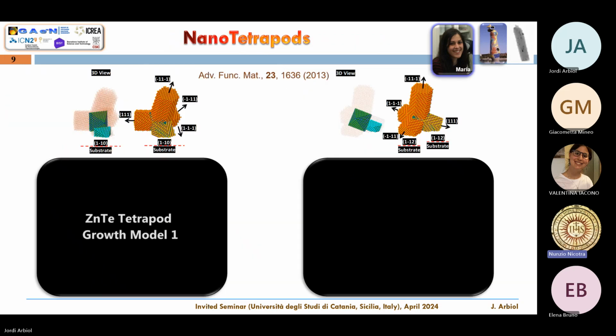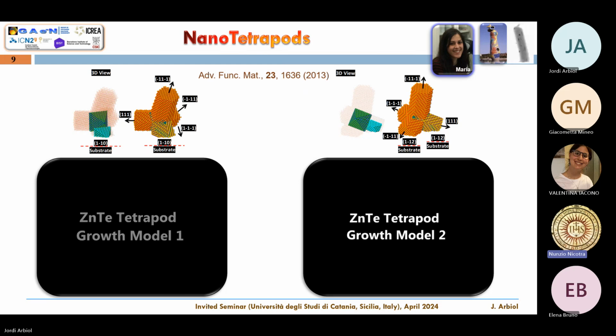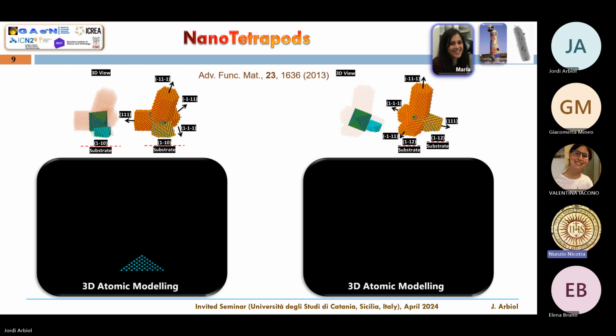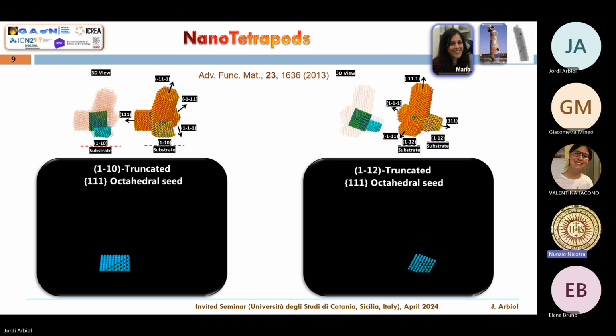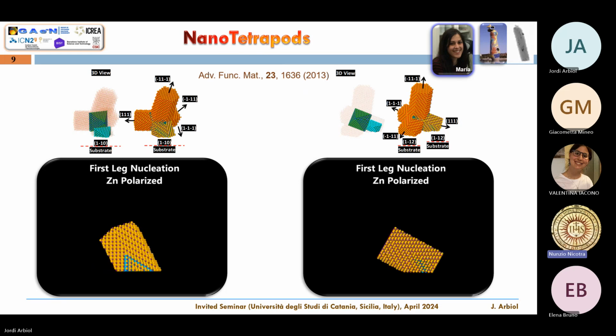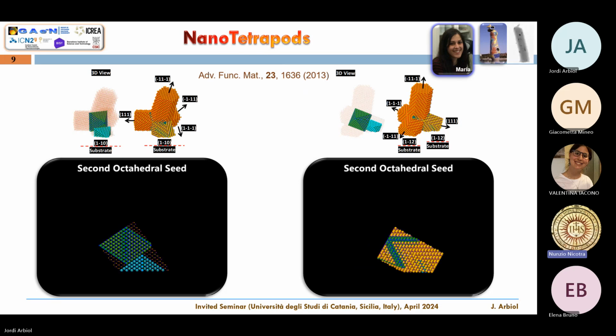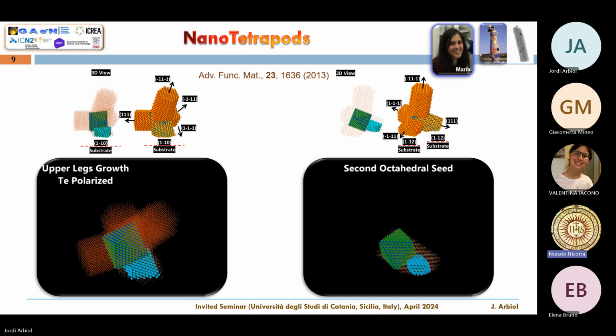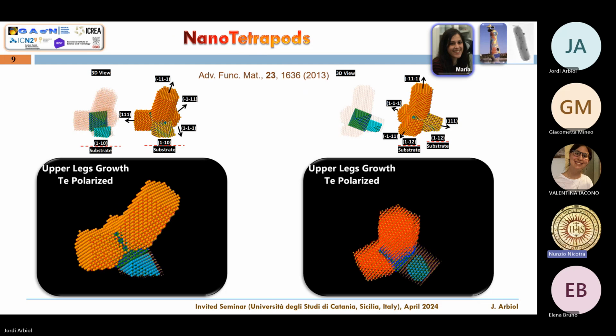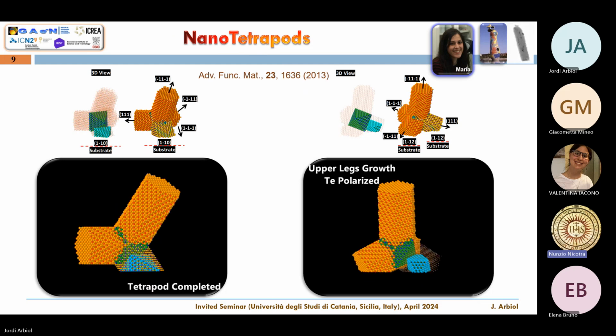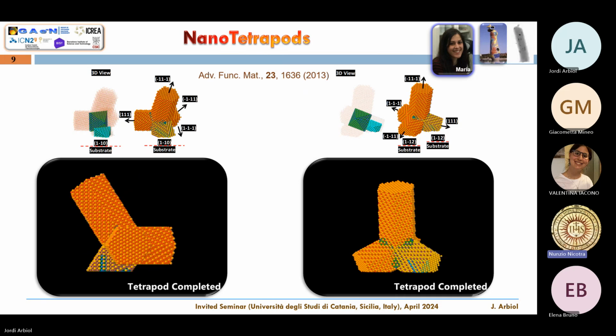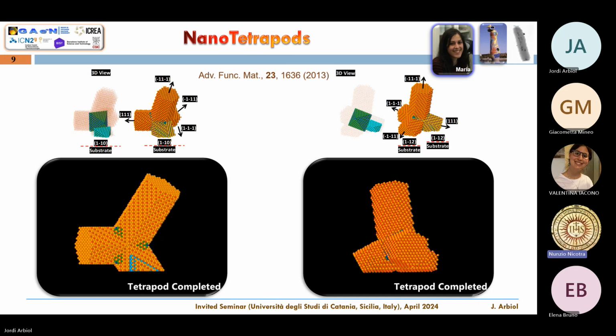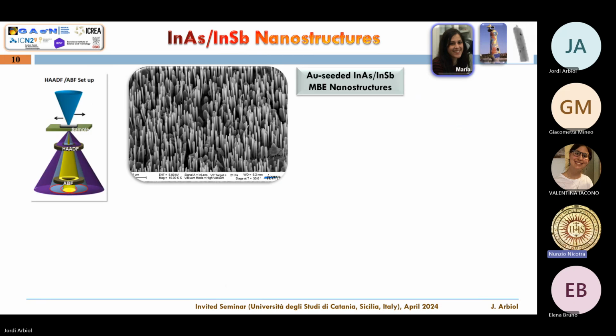But what happens if we want to create a tetrapod? So instead of having a perfect, let's say, octahedron, what we can do is nucleate a faceted or truncated octahedron. In this case, if we truncate the octahedron on the 110, or if we do it on the 112, we will get different possibilities for the facets. Then we can create a second nucleation event, creating another octahedron with 3 more available facets on the anion sides, the same here. And then depending on the different angles that you get for the different truncation, you can get this type of tetrapod or this other type of tetrapod, where these legs are just falling on top of the substrate. So it's quite easy. Just think about the anion polarity, and then you can create all these different facets. The same is here.